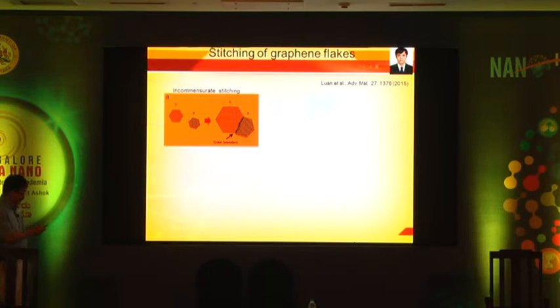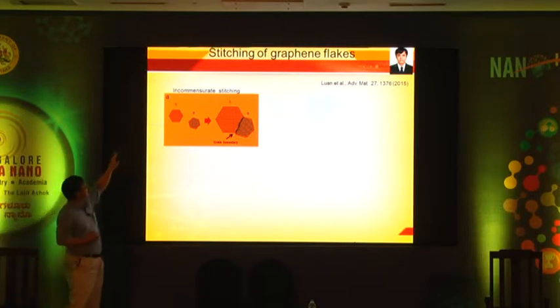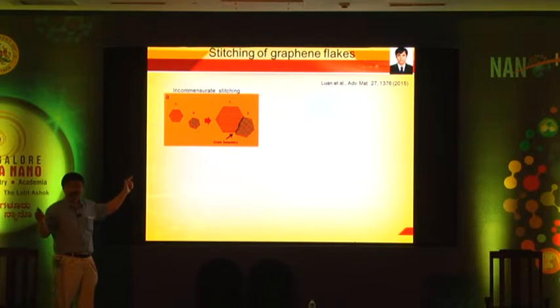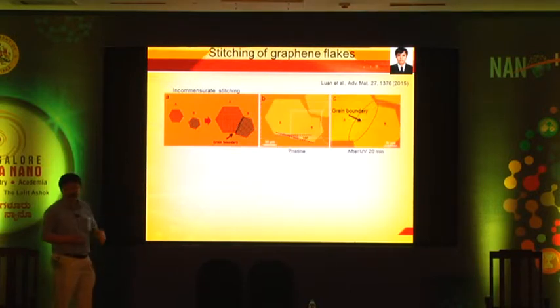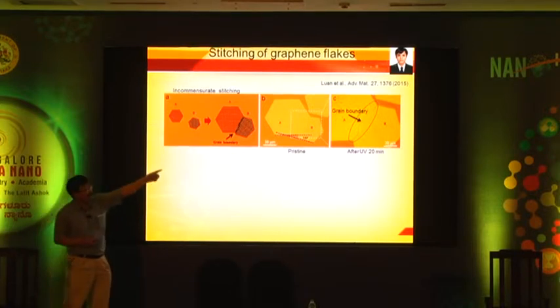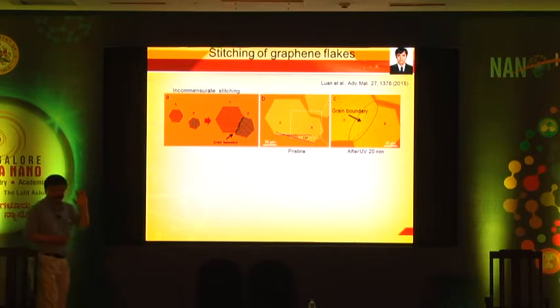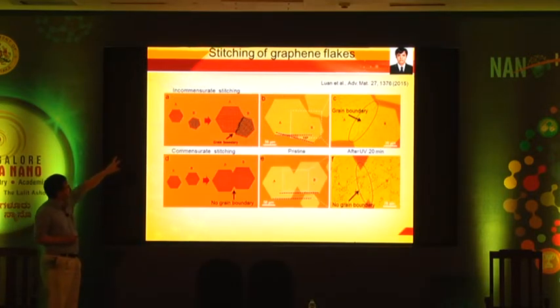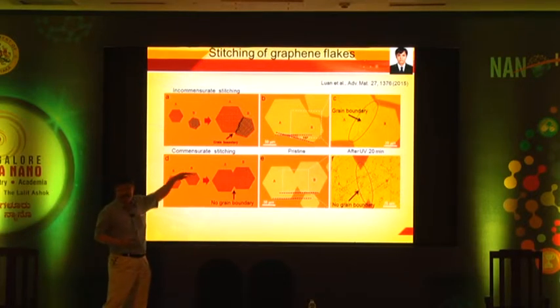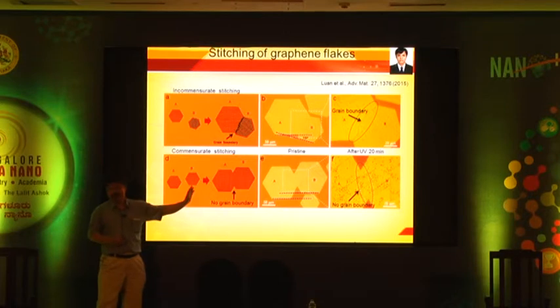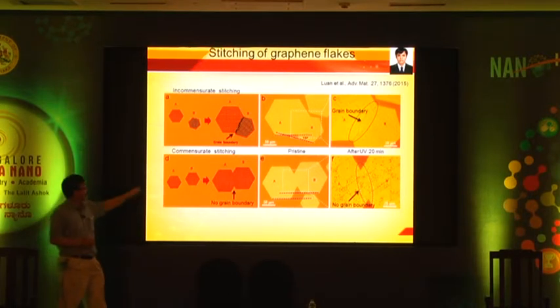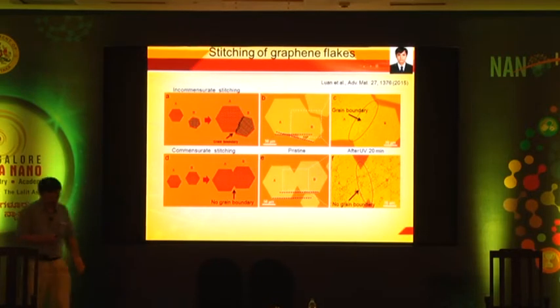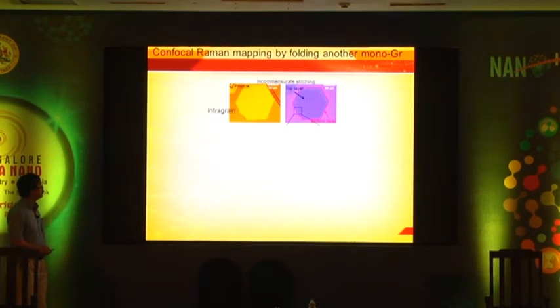So our idea was very simple. Here we have two graphene flakes with two different nucleation seeds and in different orientation. When they meet together, we form this grain boundary, and this grain boundary can be observed by using our simple oxidation technique. You see there is a grain boundary in the middle. And when you have two graphene flakes in the same orientation like this, they meet together, and you see there's no grain boundary. So the question is, how to align them together?